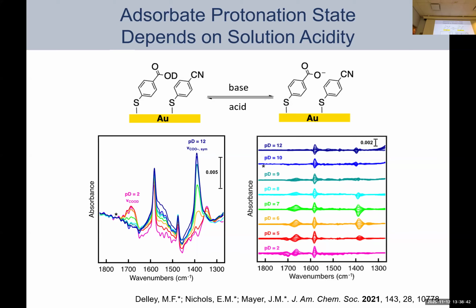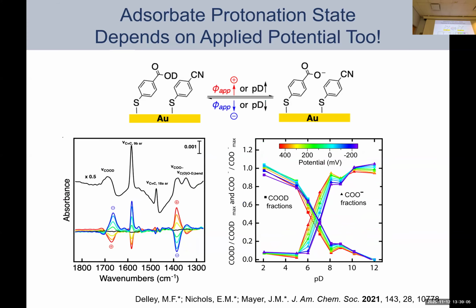And actually, for each color representing each different PD, we can now start applying different potentials. Okay, and so essentially, that's what's sort of overlaid here. That's why you see some peaks are going up and some are going down. These are different spectra now with reference to a defined standard. Okay, so that's what I wanted to show you here is how the spectra of your ATR-SEIRAS change as a function of applied potential.